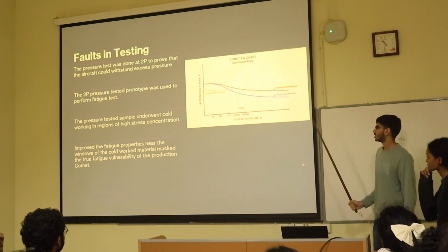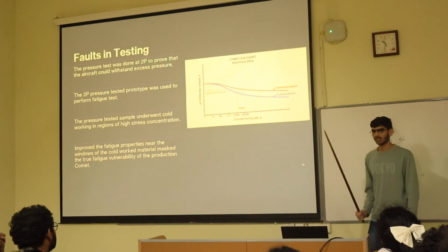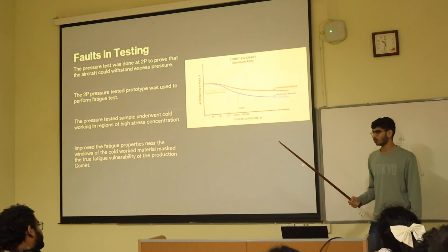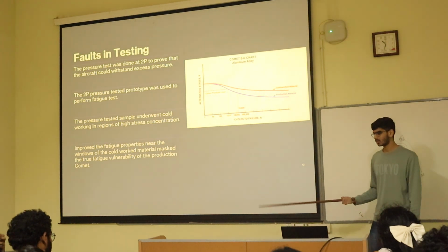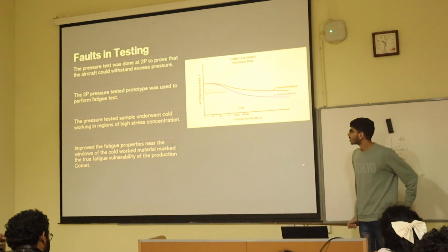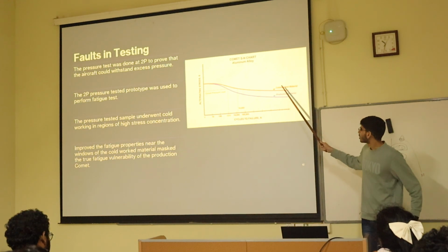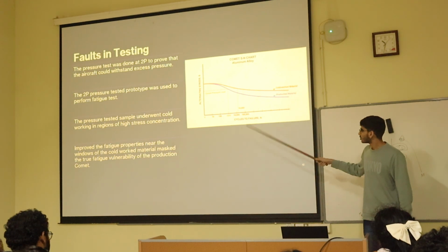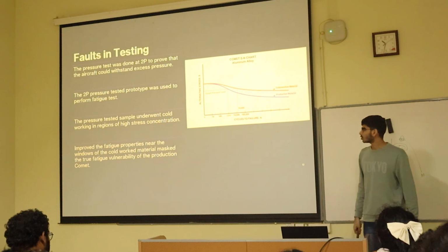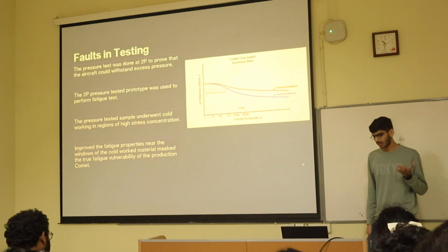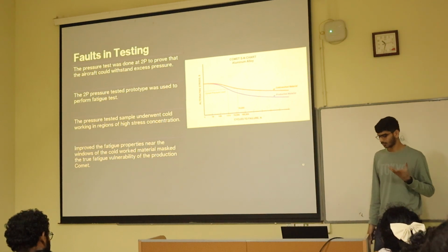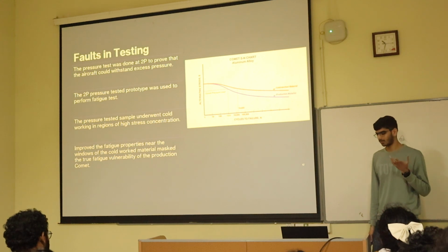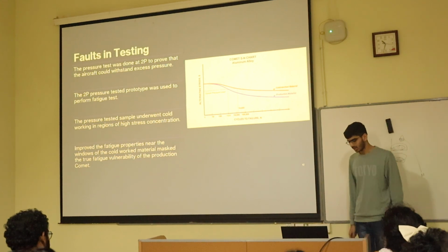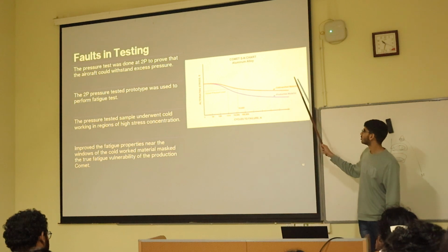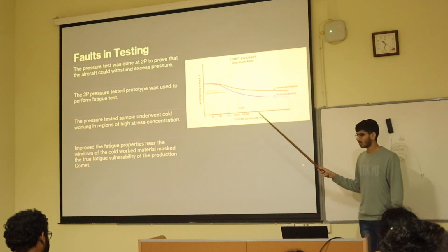There were also faults in testing. The main fault was that they tested the aircraft at twice the peak pressure, which was double the operational pressure. What that led to was that the material got cold worked. If you test the material at twice the peak pressure, the material characteristics fundamentally change. It becomes stronger, but more brittle. So when they tested the material, they were actually testing the cold worked material around the windows and around the plane.